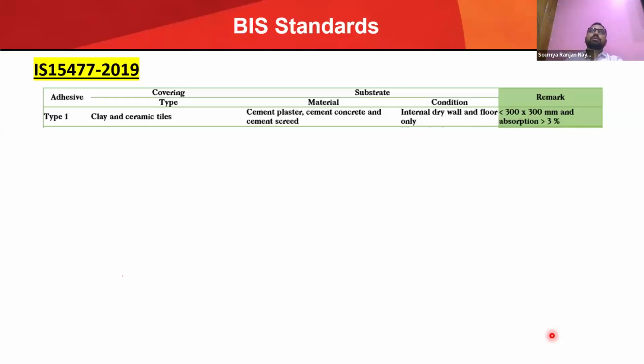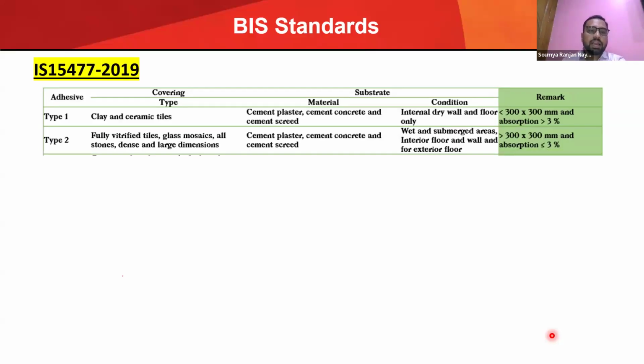Like in cement, the IS code is mentioned on every bag of cement. In tile adhesive also, on each bag of tile adhesive, it's mentioned that it conforms to this IS code and also whether it is type 1 or type 2. So type 2 tile adhesive is applicable for tiles greater than 300 mm, and it's for vitrified tiles, glass mosaics, stones, and large dimensions in interior floors and walls and exterior floors.